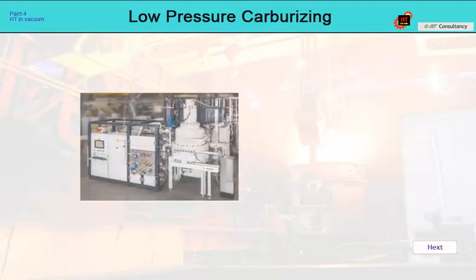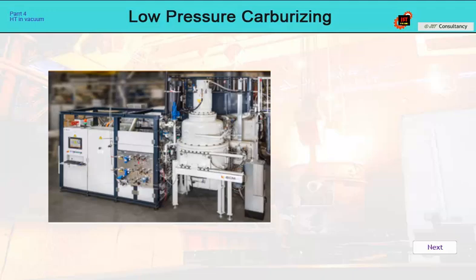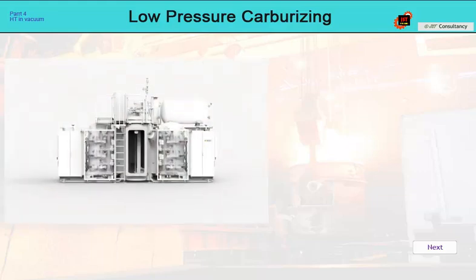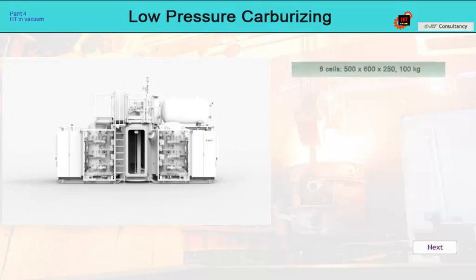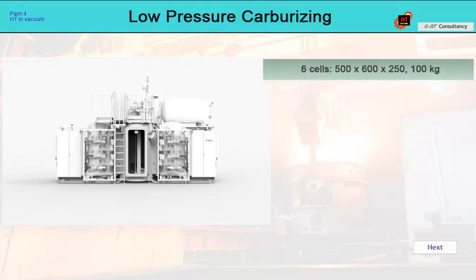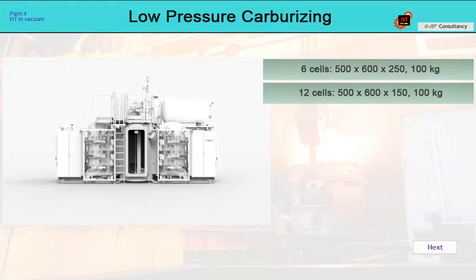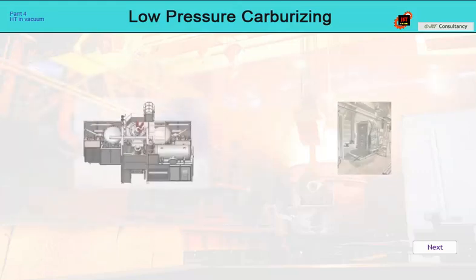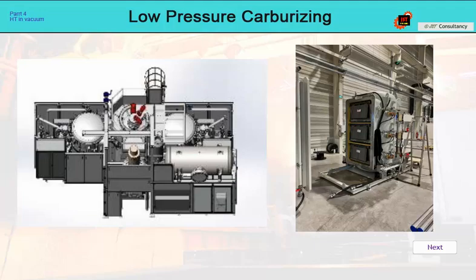The new product from ECM is the Nano system. This device completely changes the view of the heat treatment line. It works with small batches up to 100 kilograms, but their movement between the chambers is not horizontal, but vertical. There can be 6 heating chambers with dimensions of 500 by 600 by 250, or 12 with dimensions of 500 by 600 by 150. The device can have both oil quenching and 20 bar quenching in a gas stream. In this case, however, either and/or is valid.